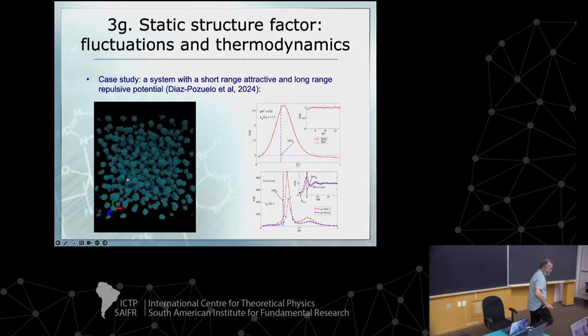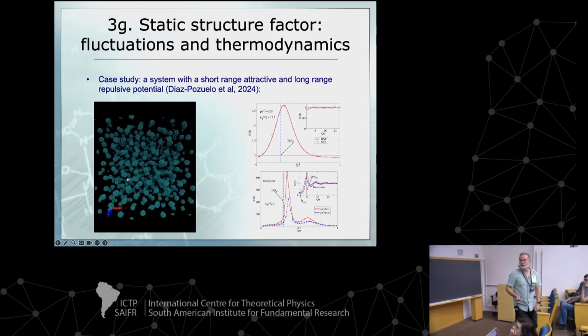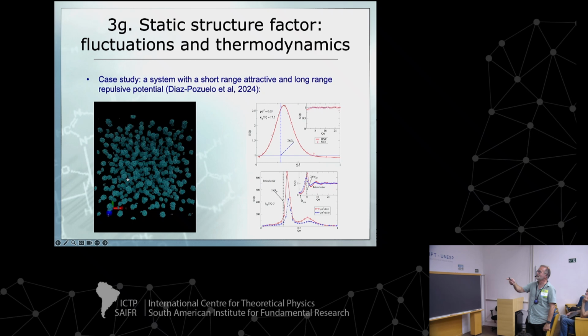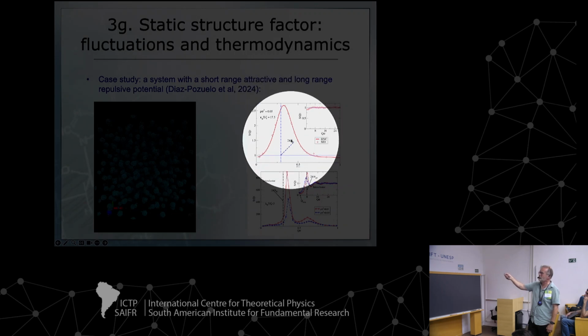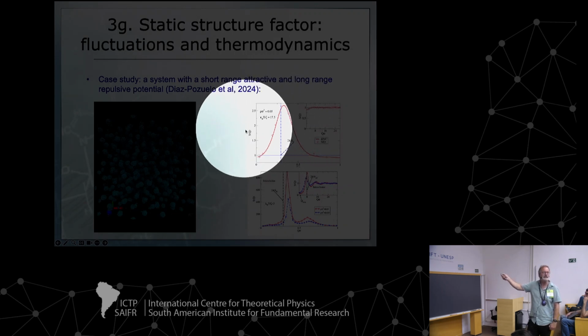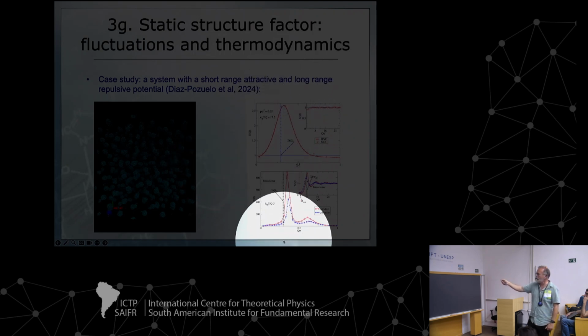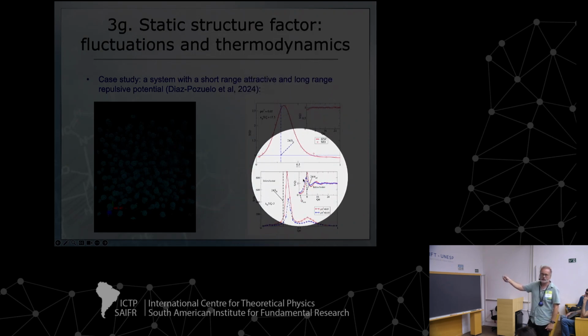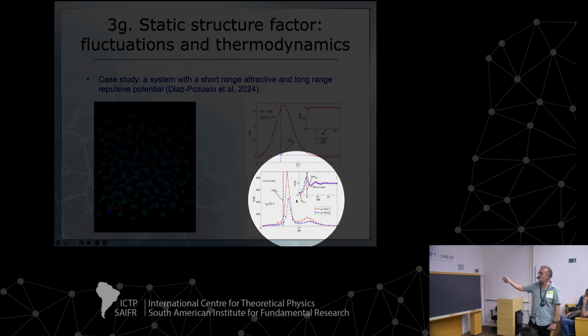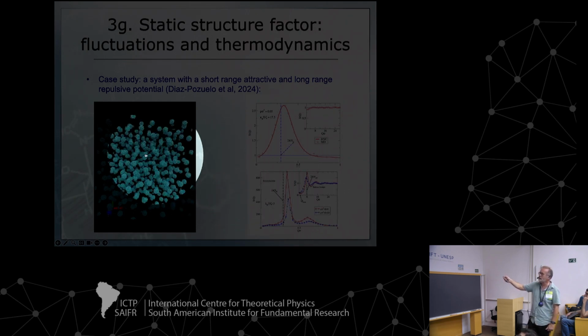Okay. So, what happens when you lower the temperature is precisely this. You have the formation of these huge spherical clusters. They are relatively big. And the structure factor goes from this one that is telling you, well, I want to associate but still is not associated, its association is not visible to the eye, to this one here, which is huge. It's almost a divergence, right? And the position of this peak reflects the distance between the clusters, right?